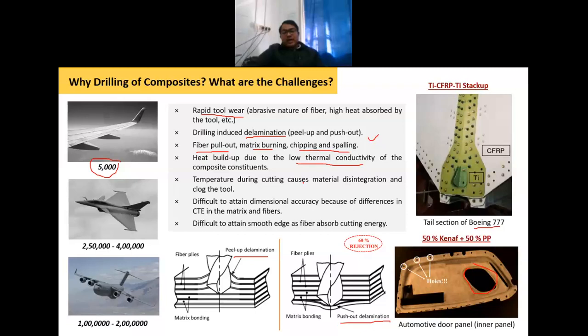So what will happen when we do the drilling operation? Due to physical interaction of the cutting tool with the composite laminate, there will be a temperature generation. In case of metals and alloys, most of the temperature is carried away by the chip, maybe around 75% of the total heat. The remaining amount of heat is transferred to the cutting tool and the workpiece material. But here, due to the low thermal conductivity of these composite materials, the heat that is generated is mostly concentrated on the cutting tool, and it will have a detrimental effect on the life of the tool.